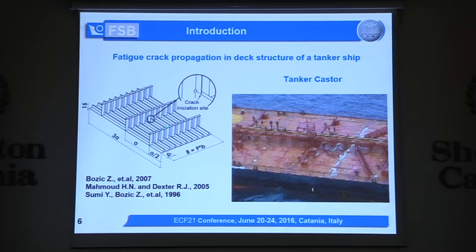The deck turned upside down, so you have your plate and longitudinals and bulkheads, and then you have complex geometry here, where welds are meeting each other, so stress concentration sites. So here a crack can initiate and the cracks propagate through the longitudinal and enter the deck plate. And when you have this at several locations, these cracks may join, and this is what you have as a result. This is a 20-meter-long crack in the Castor tanker ship.